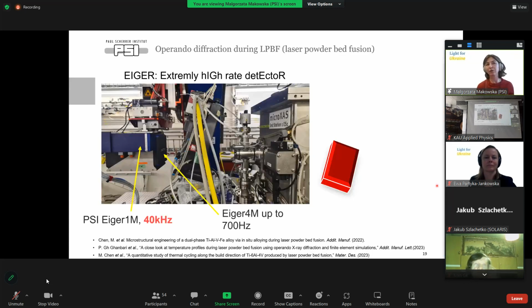Then what we do, which is also important for maybe applications at micro beamlines, thanks to the fact that we have a very small beam, is that we can actually capture these small areas also operando, where we melt with the laser during this 3D printing. The molten volume is very small, and then the volume which is solidifying is also very small. So to see it in situ, we also have to use the microbeam. And this is an example of the operando diffraction experiment during 3D printing.